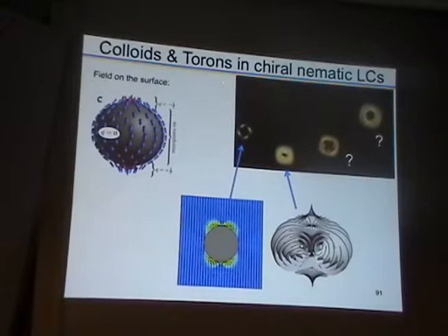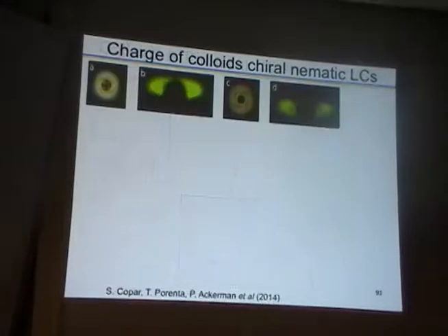Now, it is important to note that this example of a particle with boojums satisfies the mathematical theorems for what we expect for the net charge or winding number of defects on the surface of the particle. But the charge of the particle as a bulk hedgehog charge is equal to 0, because it is easily embeddable in a uniform director field; we only have surface point defects.